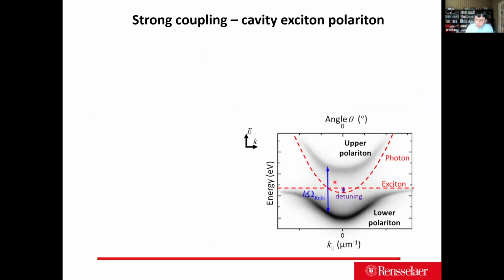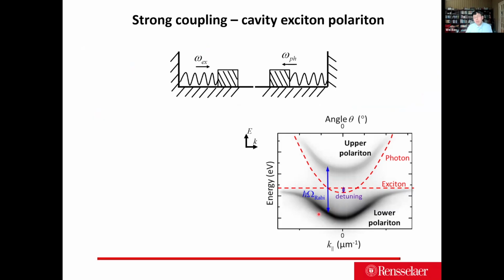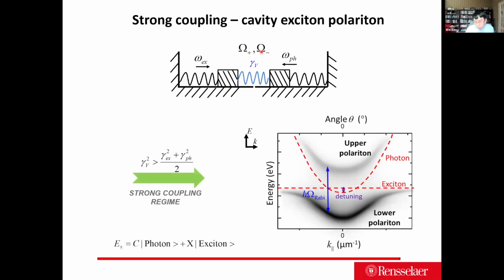So in other words, to understand the cavity exciton polariton, here is the dispersion, and we have the exciton and photon detuning and the Rabi splitting. One can think of it even in a classical way without going to complicated things. We have two linear oscillators, one is the exciton, the other one is a photon. Now we bond them with a spring, with a much stronger strength, and we form hybridized states called the upper polariton and the lower polariton in the strong coupling regime.